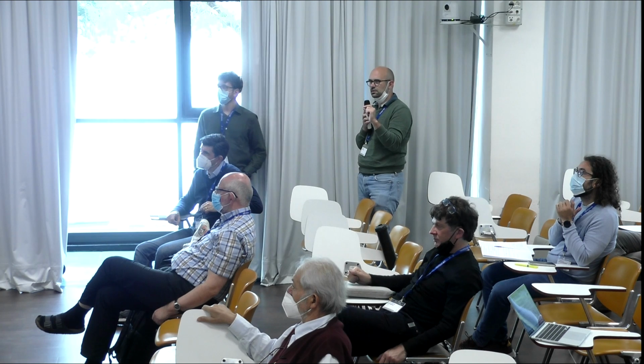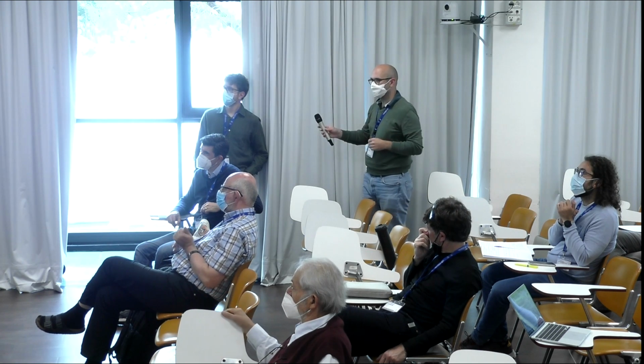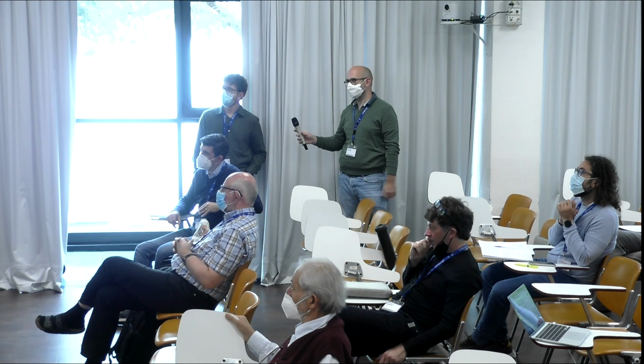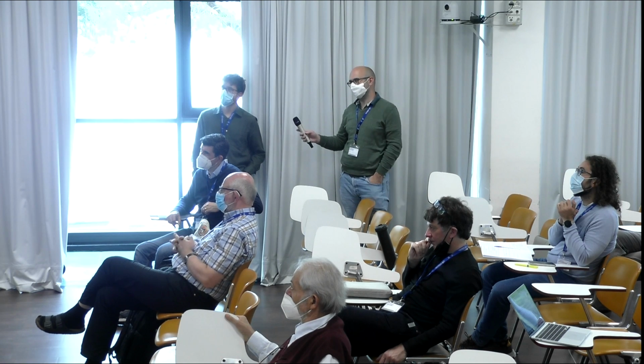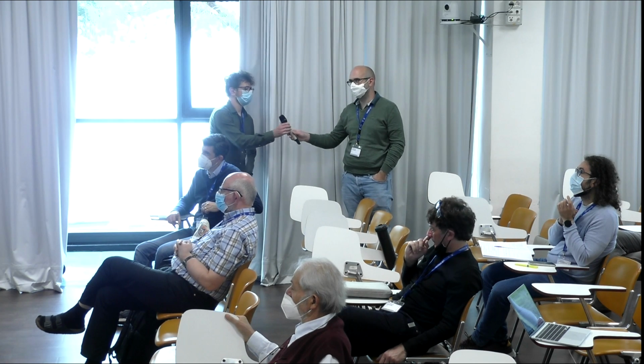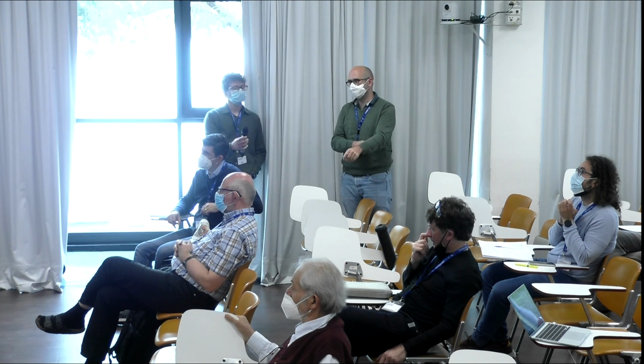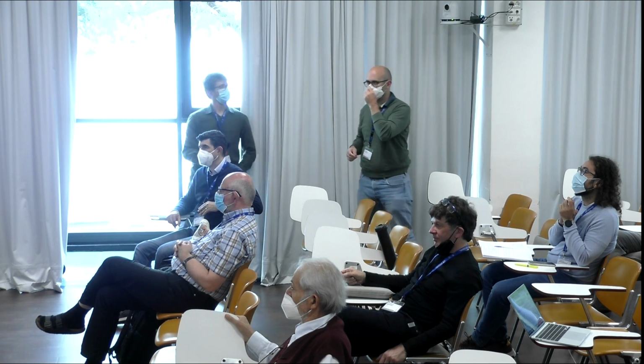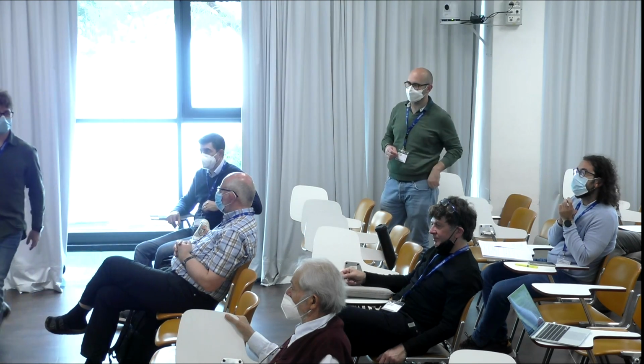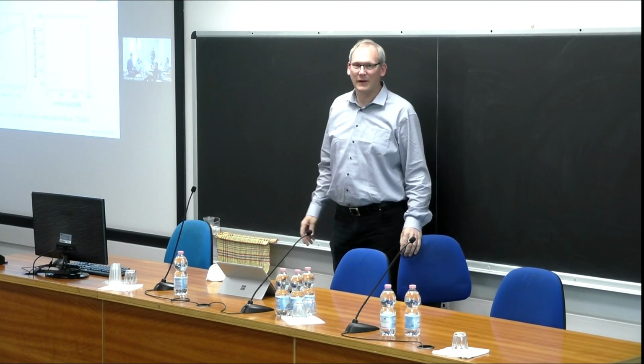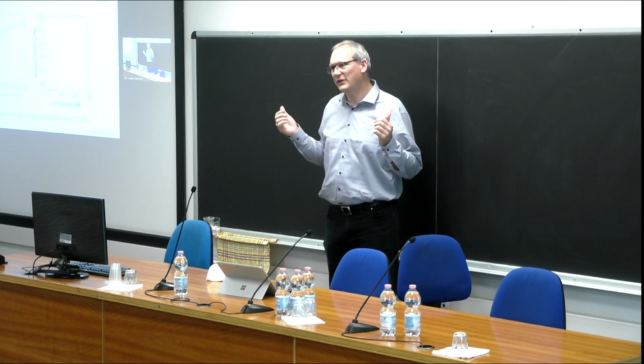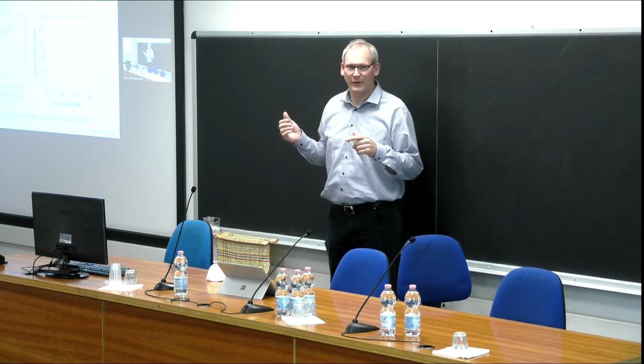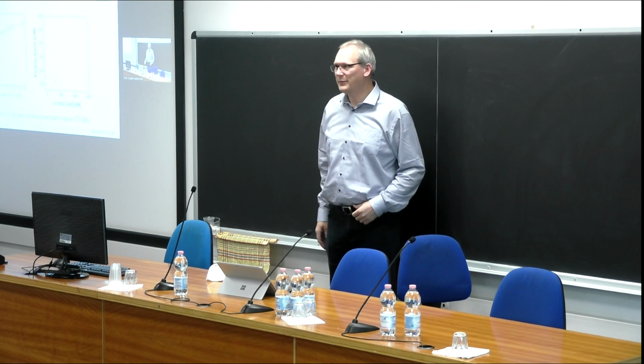Pretty much. Let's say, I don't think that the pressure is that high in the silicon. It's only that high in the local apex of the silicon oxide. And we do have plastic deformation of the silicon oxide, absolutely. And we can even show you the number of silicon bonds that all of a sudden pop up. So actually the average configuration of the silicon oxide changes at this point. But it's really not such.